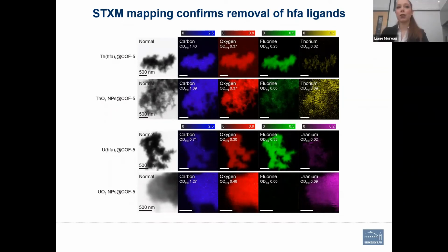Right, so that's something that is interesting, and I won't talk about that today, but one thing that we've looked at subsequently is making particles of different sizes using this methodology to see if there is some sort of disordered core-shell structure going on. We also did some comparison, which I didn't talk about either. It's not really a great model because we don't have a totally identical symmetric system here, but we did use the method developed by Calvin to look at decreases in coordination number as a function of particle size. And it did appear that there were